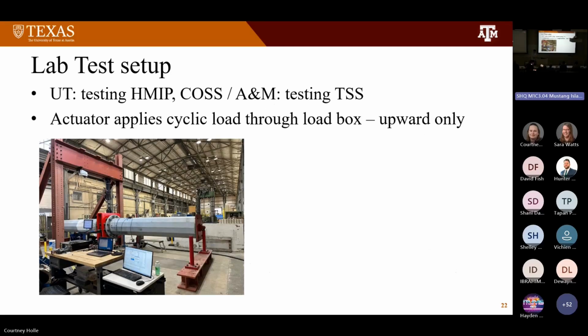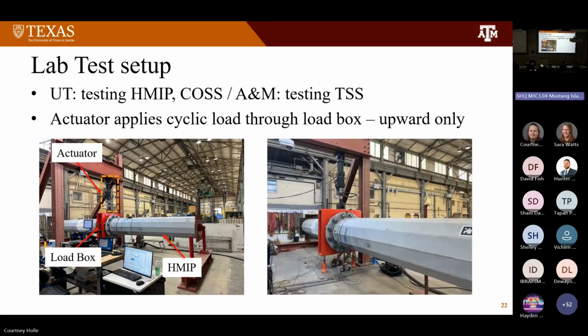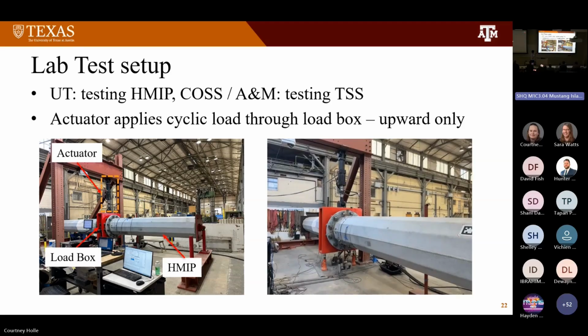At UT, the experimental test was planned for HMIP and COSS, while Texas A&M is conducting testing for TSS. The test methodology is pretty similar, so I will describe the general test setup. The test specimens were connected to both ends of the load box, and then cyclic loading was applied through an actuator. On the right, we can see the video of the fatigue test. We can see that the actuator is pulling up the loading box, so the top side of the test specimen has tension stress.